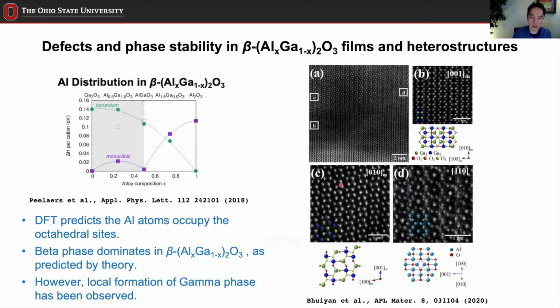But then there's a problem, because when you are trying to grow these aluminum gallium oxides, you don't always get the structure that you want. Peelaers explored the structure a couple of years ago, and this is a very important paper predicting the stable phase when the alloying is happening. What you're looking at is sapphire, which has the corundum structure, and gallium oxide, which has the monoclinic structure. Which one is going to win? That's the question, so he calculated that. If you calculate it as a function of the aluminum concentration, monoclinic is in fact going to be stable up to an aluminum concentration of about 70%.